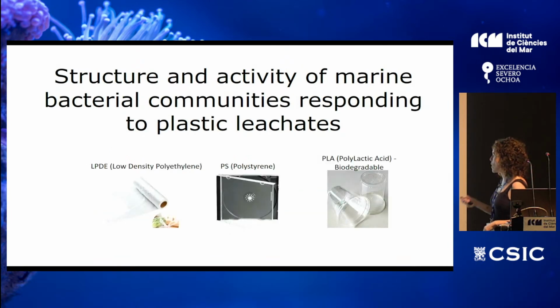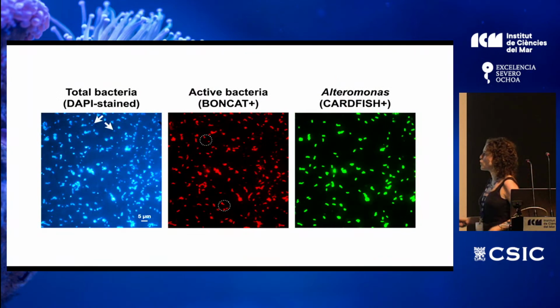To answer this, we used different types of plastic, but all of them were new. You have seen that there are differences between new and aged already. Here is just to show how this methodology looks. When we stain bacteria with DAPI, a stain that stains the nucleic acid, you can see all the bacteria fluorescing in the microscope. Then when you use BONCAT, you have the same bacteria, but only those that are active, synthesizing proteins. And then with CARD-FISH, you have the same picture, but only showing those bacteria that are, in this case, Alteromonas, the phylogenetic group that we tried here. So for example, here you can see these circles. These are bacteria that are here, but they don't appear here.